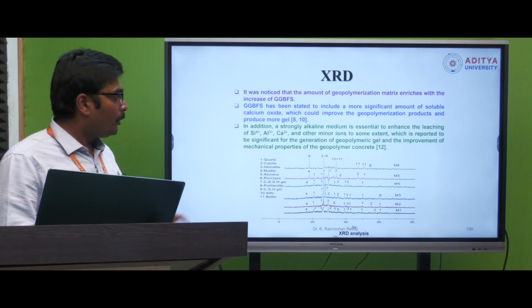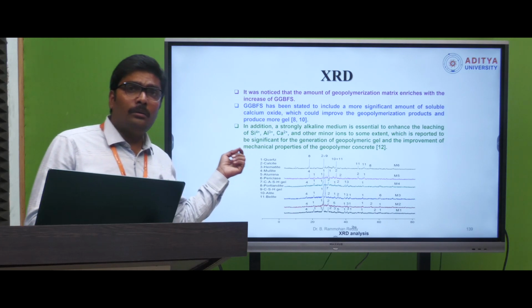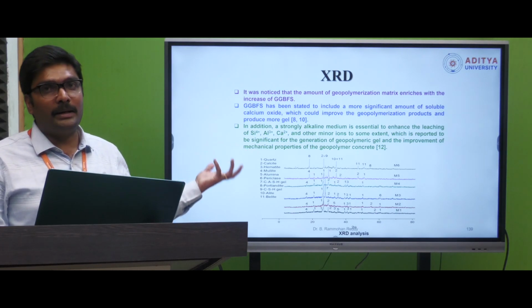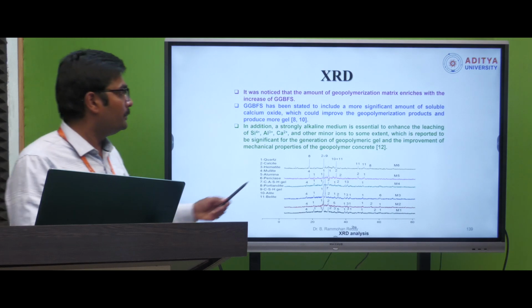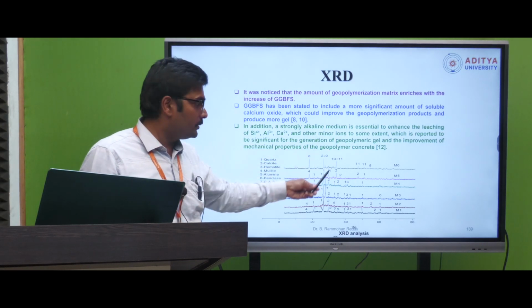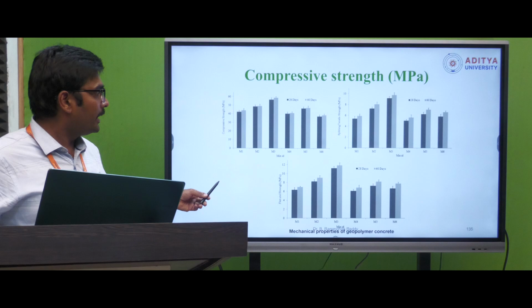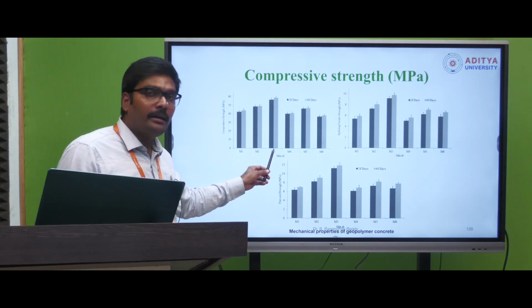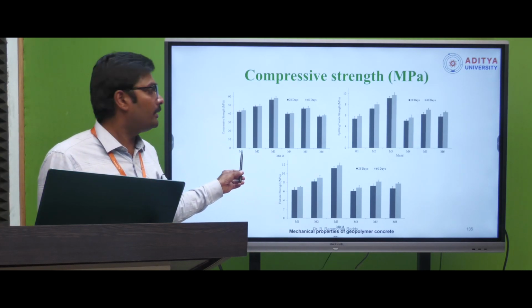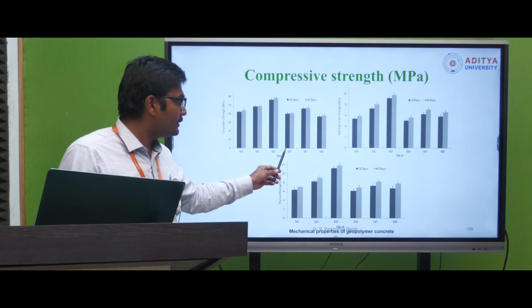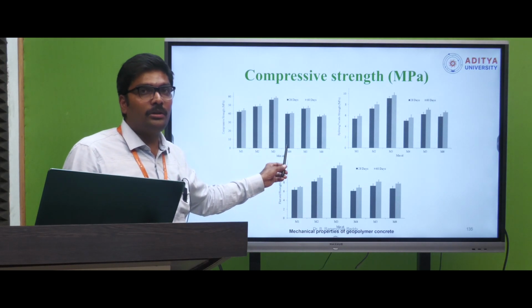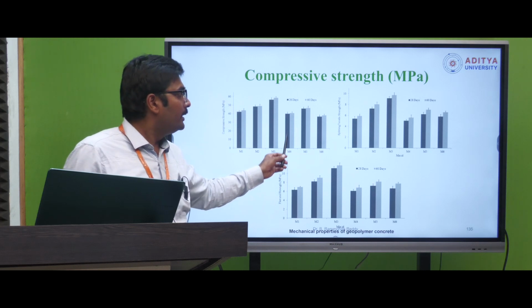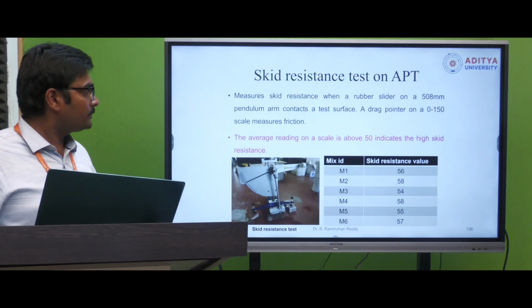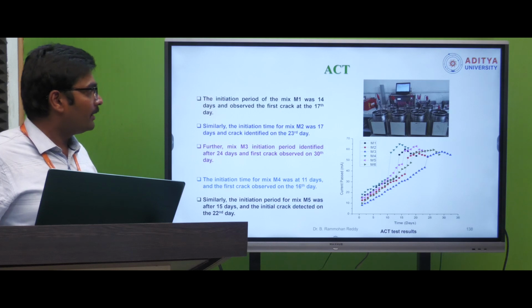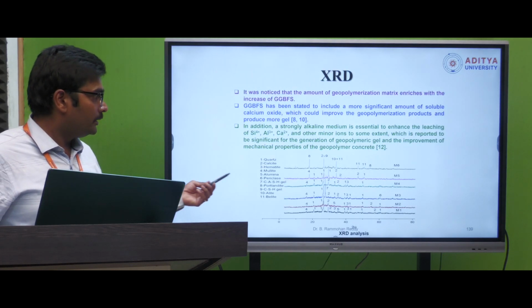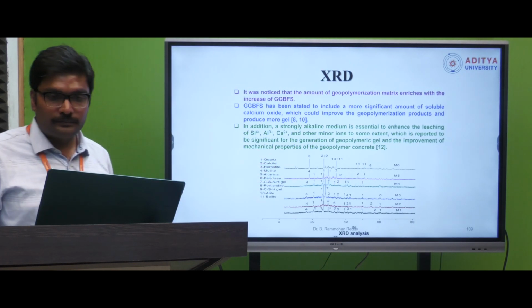That's why a 0.45 solution to binder ratio gave better results. Further increasing the alkaline media reduces the compressive strength. That's what this slide indicates. So these 3 mixes with 0.45 solution to binder ratio gave better strength properties. Further increasing the solution to binder ratio from 0.45 to 0.5, the strength values are reduced. Up to a certain limit it will be okay, further the strength values are reduced. That's what this sentence is indicating.